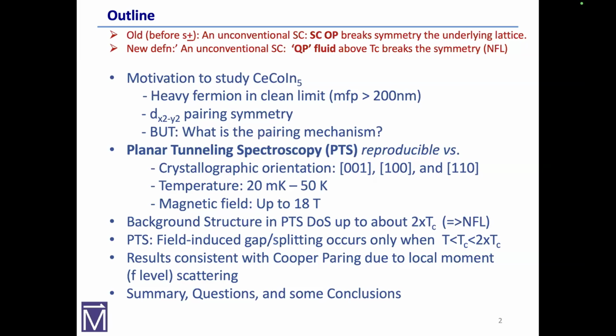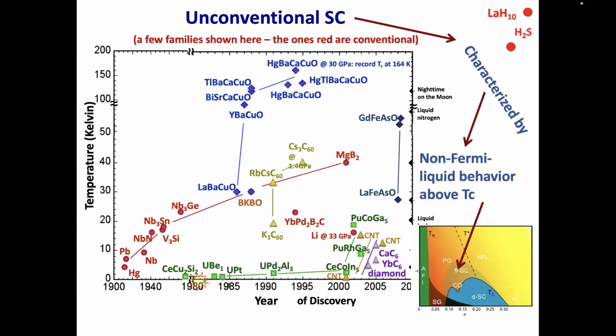What I'm stressing in this talk is that above Tc, about twice Tc, where Tc is 2.3 K, we see a very interesting structure. It turns out that we get a field-induced splitting or some field-induced gap that only occurs above Tc, but below twice Tc. So there's like a magic area in there. And I'll point out, and I don't have the hard theory yet, that the results are consistent with Cooper pairing due to Kondo scattering. And then I'll go through summary questions and conclusions. Now, I added something there, but I lost it. Oh, it's in the next slide.